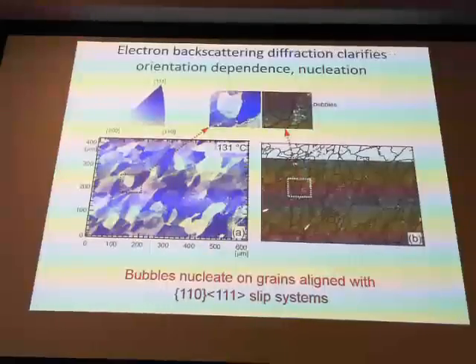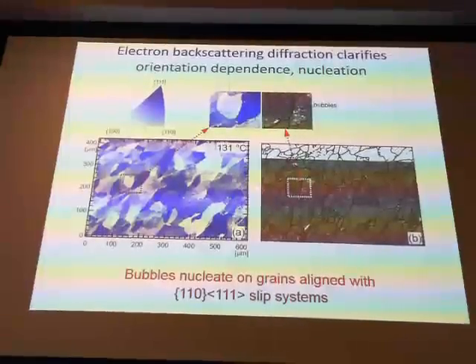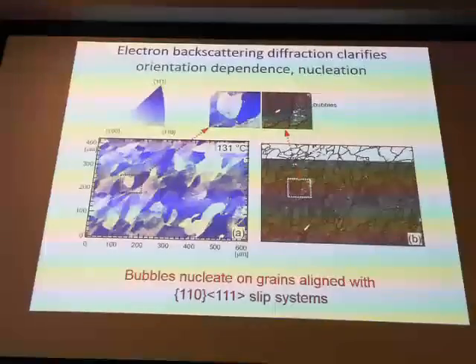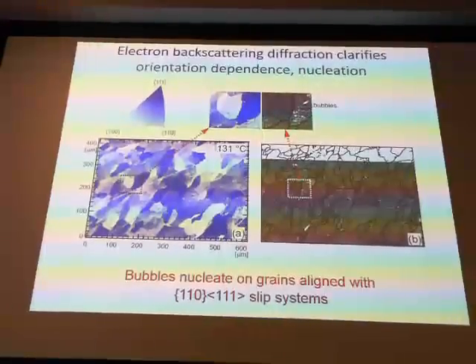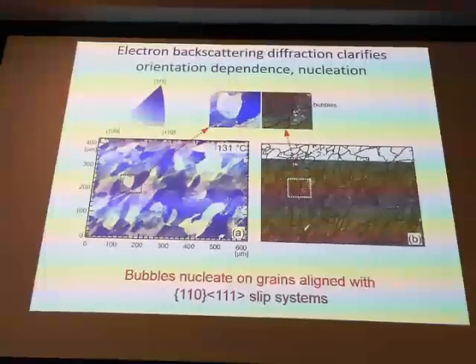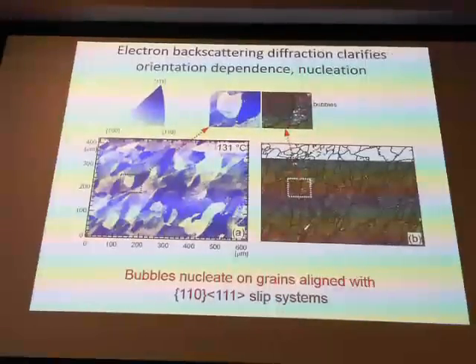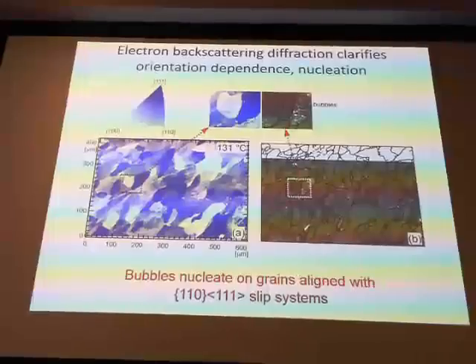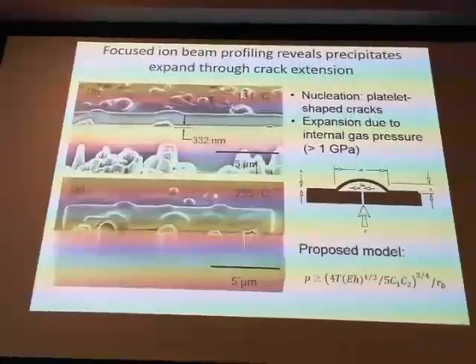And we found that the formation of bubbles very strongly coincided on grains aligned with this 110-111 slip system within the material. And so, here's a very clear example where you have adjacent grains, where there are bubbles here but none here. And so it seemed like a potential nucleation mechanism here was that the hydrogen would accumulate at some defect, and if the grain structure was aligned with this particular slip system, it could push the material up and away from the surface and nucleate a near surface crack or a bubble as a result.